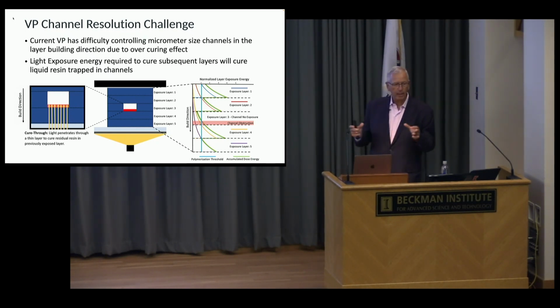You can control the light in the XY plane with pixels. That's easy. How do you control light in a Z direction? I don't know how to do that very well. You can put all sorts of opacifiers, but then your cure rates go down, and it's a problem. We're solving this with fluid mechanics because the resin coming through the port is fully oxygenated. And we can deliver way more than we need at the build surface and keep the amount of light that exposes that resin to a minimum and avoid curing the channels.